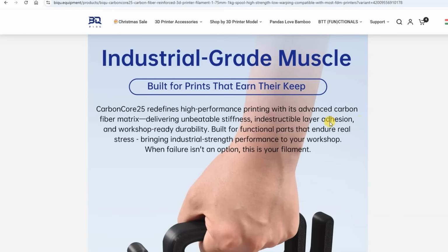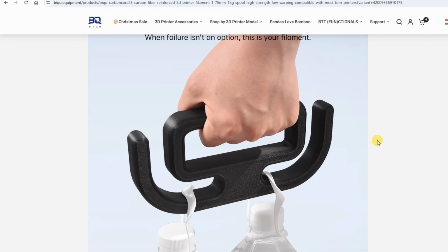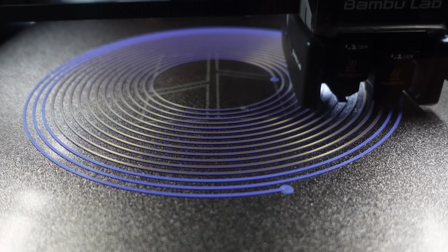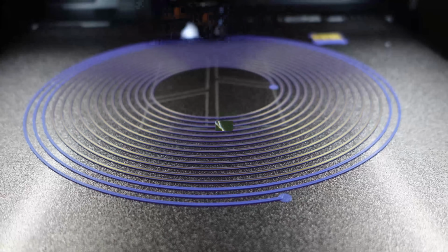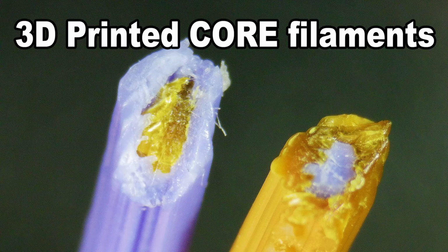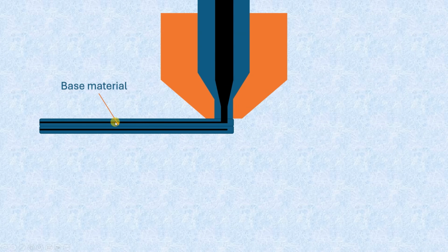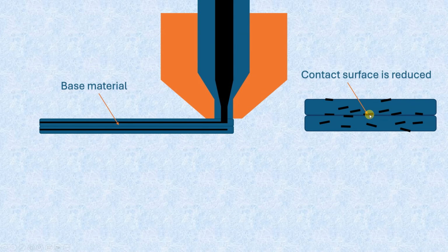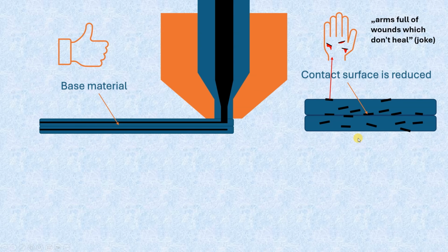Another advantage of the core filaments is better layer adhesion. And I actually tested this in a separate video when I printed these DIY core filaments, because outside we have the skin from the base material. Because carbon fibers will usually reduce this cross section and reduce the layer adhesion. But if only the base material we have the contact, and because the flow is laminar, we will have better strength along the z-axis.